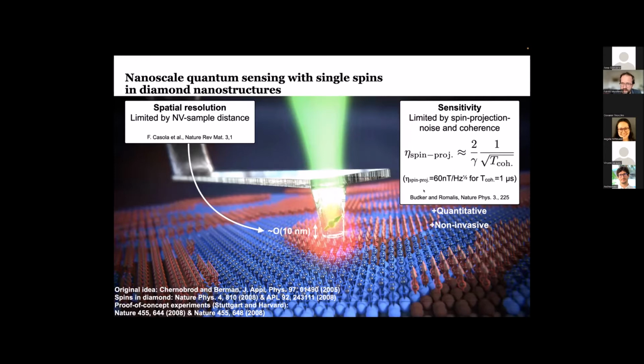And if you plug this in, you see that an NV magnetometer, a single spin magnetometer like this, can achieve sensitivities on the order of 60 nanotesla per square root of hertz. So it can resolve changes in magnetic field of about 60 nanotesla within 1 second of data acquisition time. That, of course, requires that you can implement such a quantum mechanical measurement scheme and this quantum projection limited sensitivity, which in our case is limited by the efficiency of the optical addressing of the NV spin. You've heard before that we perform optically detected electron spin resonance in these measurements, and how well we can address the spin depends on how well we can couple the fluorescence emitted from this NV spin to our detector that's sitting somewhere above the scanning probe.